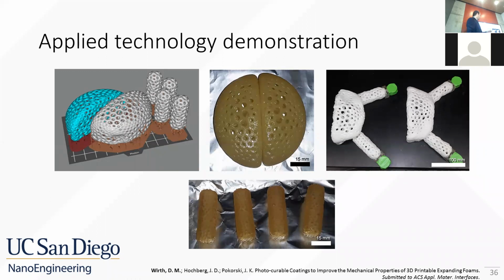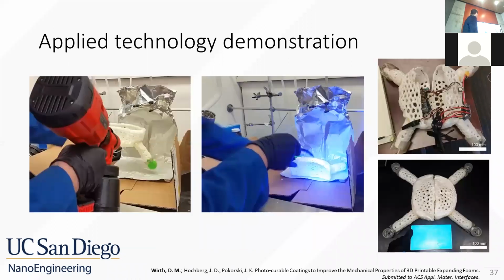The motor mounts were actually printed using conventional mSLA printing because they required a little bit higher tolerances. Here's the coating procedure: you just spray them with an ordinary cordless paint sprayer and then cure them using a UV light source.